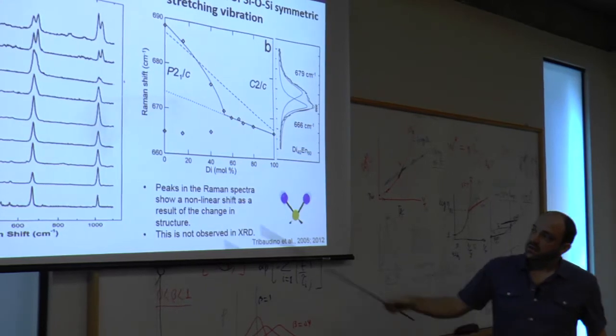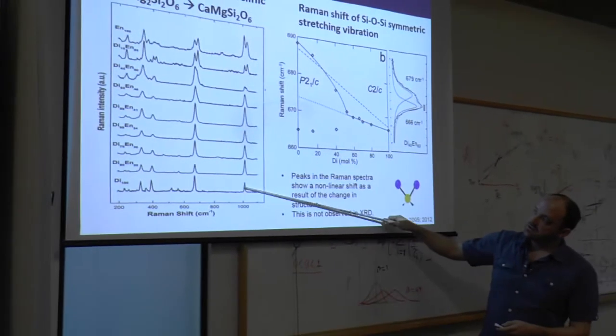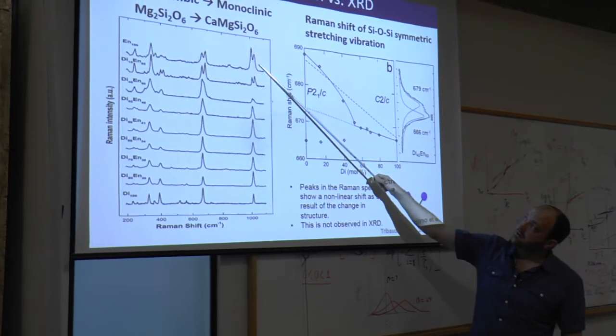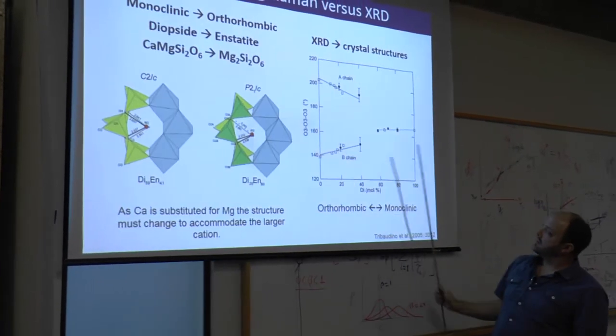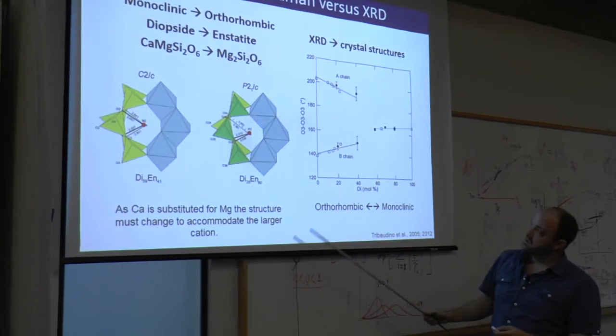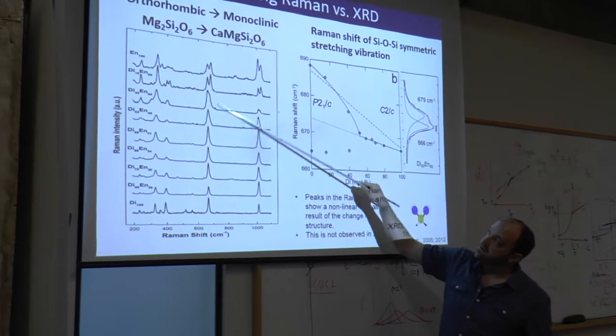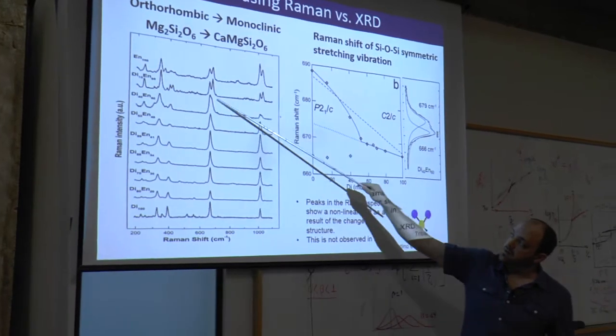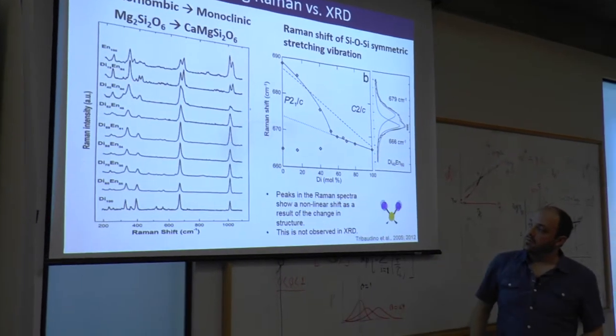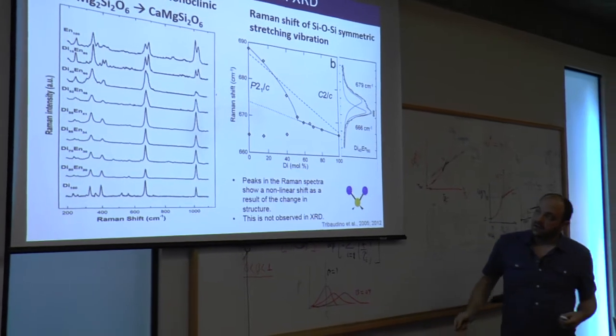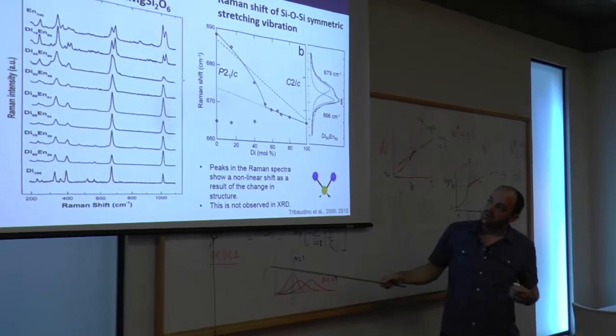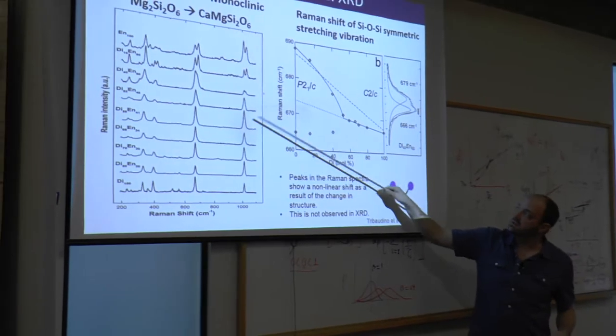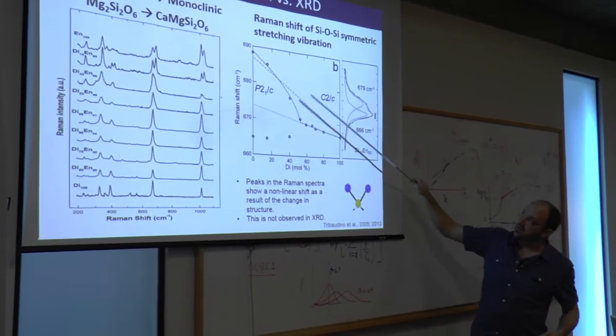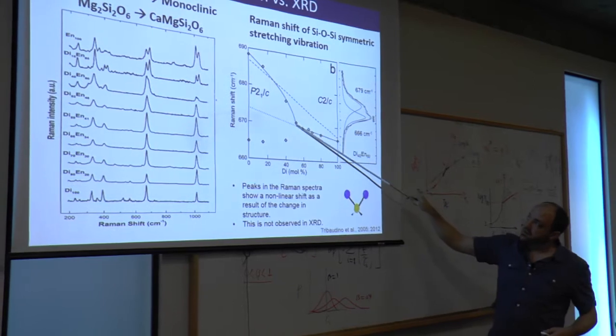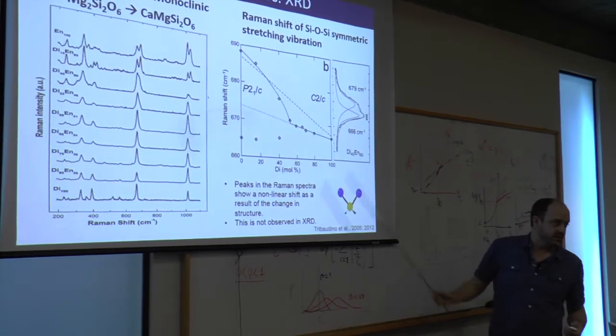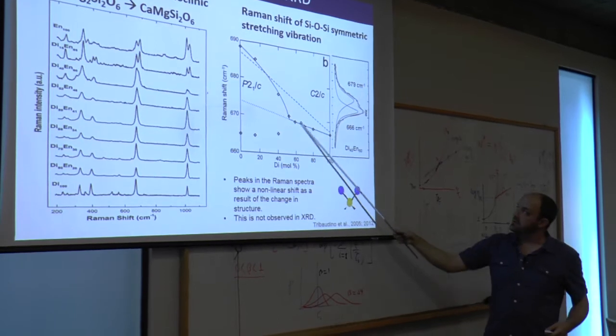We see a dramatic change in this angle. With Raman, here's the Raman spectra of the same composition. So this is diopside rich, this is enstatite rich. Here we're going from diopside rich to enstatite rich. And you see that these with two chains show a splitting of the strongest bands in Raman. When they look across this compositional suite at the shift in the position of these, you actually get quite a nonlinear shift. You can draw this nonlinear shift right to the point where you get this phase change, and they collapse into one band.